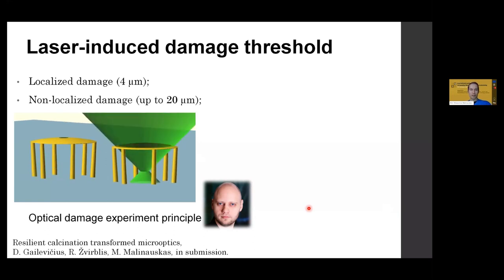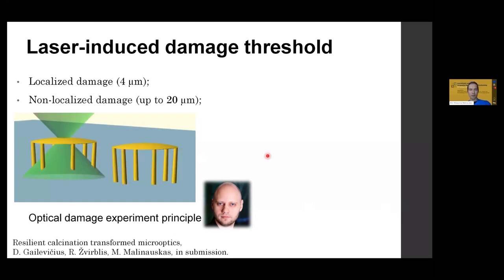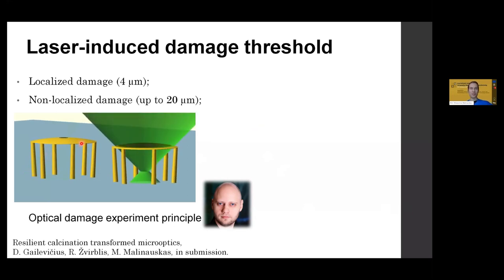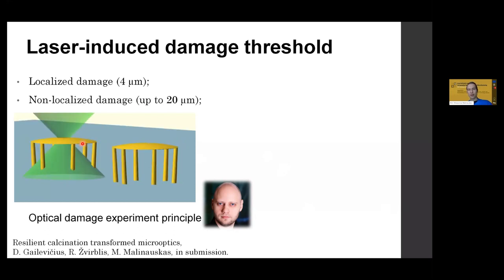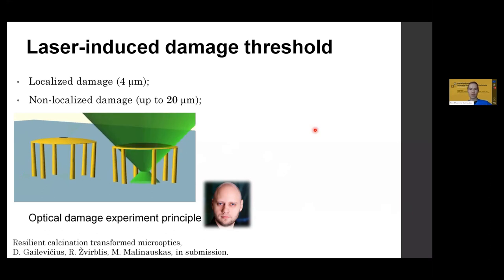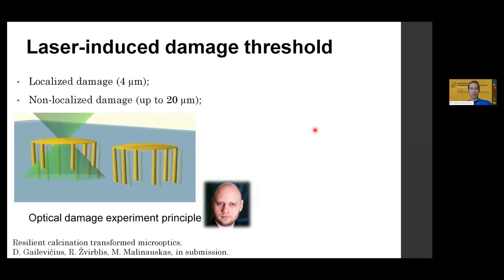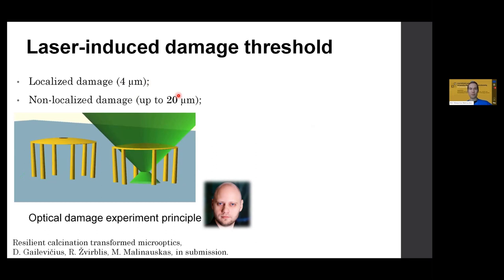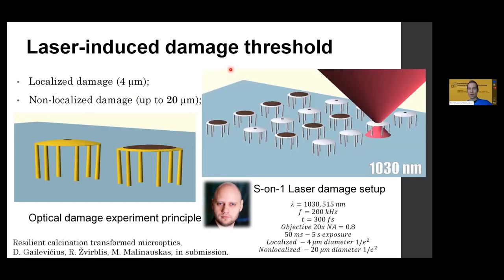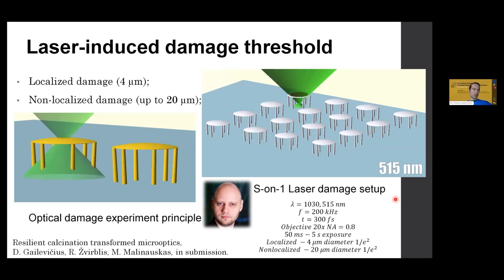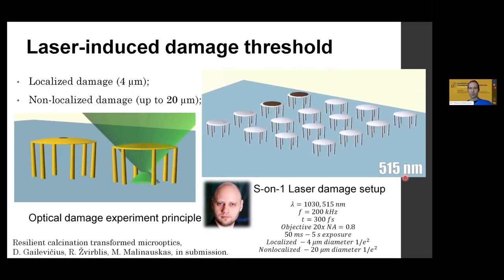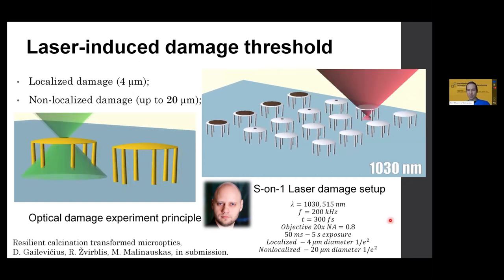So they made an extensive study of optical damage experiments on the produced micro lenses, both focusing into the lens itself and checking next to it how much non-focused light the produced micro lenses can sustain. So two distinguished cases: localized, around 4 micrometers, and non-localized, up to 20 micrometers or so. To have some statistical repeatability, an array of micro lenses was made, and all of them were individually tested using the same laser fabrication setup.